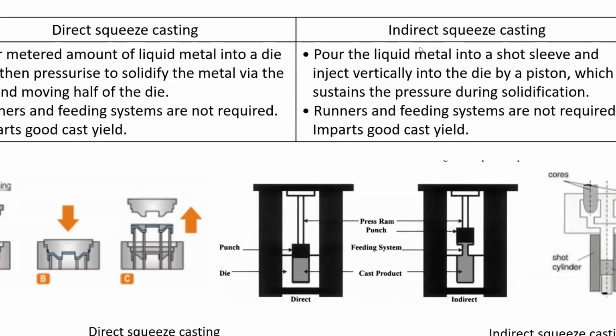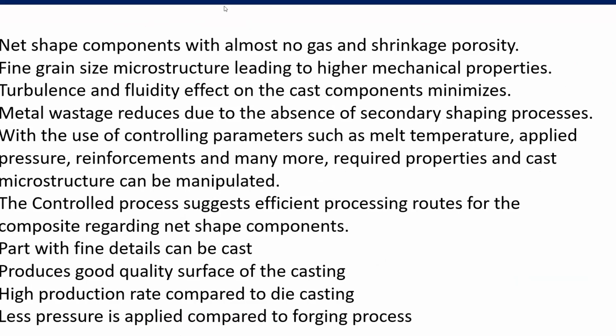So there are direct squeeze casting and indirect squeeze casting. Direct means the pressure is applied directly onto the component. In indirect, we have a feeder system through which the force is applied to the cast product. There are a lot of advantages of squeeze casting, especially no shrinkage porosity or gas porosity, fine grain structure, and minimum turbulence and fluidity effects. However, the limitations are high initial cost, limited size and shape complexity, and very high tooling cost.